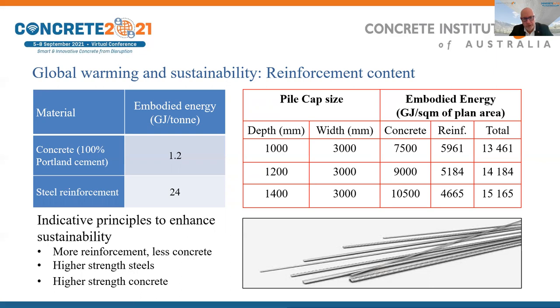And there, I've got a table here that gives you some details. In addition, we've also found that embodied energy is reduced using higher strength steels and indeed using higher strength concrete. Not in all cases, but as a general rule, and a guideline, perhaps something to take forward.